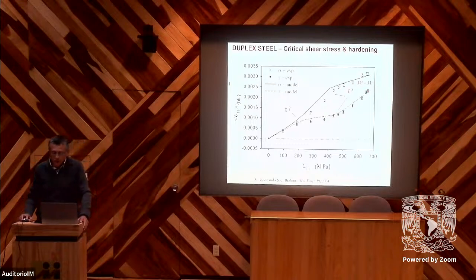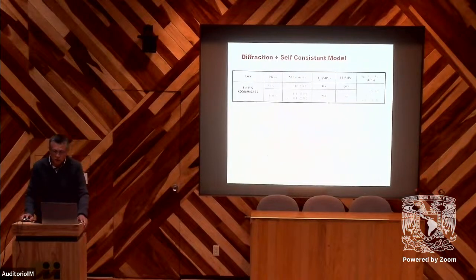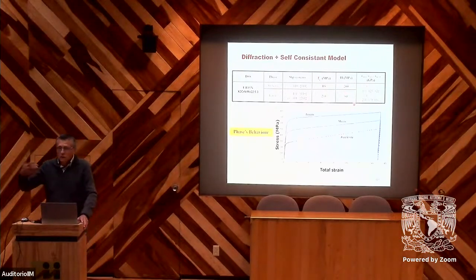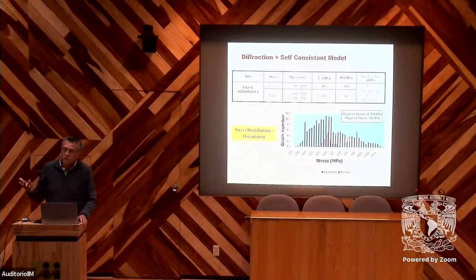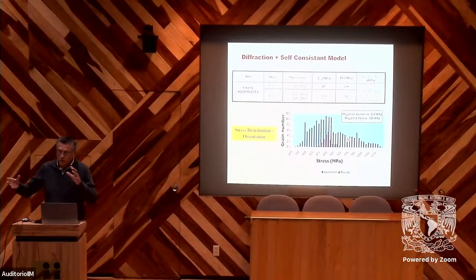Now if we compare the diffraction data and our model, we can get the different parameters of the two phases. We can observe that the critical shear stress is higher for the ferrite than for the austenite, and the hardening is higher for gamma than for ferrite. So we can then draw, for example, the tensile curve, and see the behavior of the ferrite and austenite. We also know the orientation of our crystals from the beginning of the model, so we can get the distribution of the stresses in the two phases as a function of the orientation of the grains. We can see that we have a very large range of values of stresses.